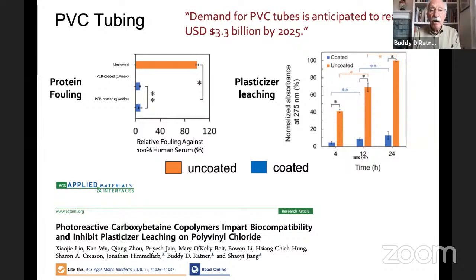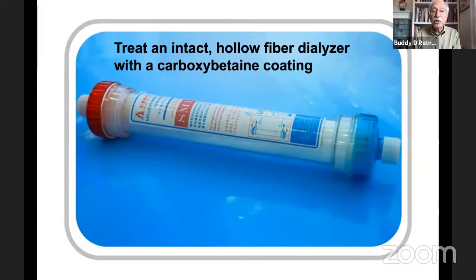But the orange bars in this are the uncoated or control PVC. The blue are coated. And if we look at again, I mentioned we could reduce protein fouling. You can see that our polycarboxybetaine coated materials, the blue, have much lower protein fouling. That's off to the left. Off to the right, we look at plasticizer leaching. And again, the polycarboxybetaine methacrylate, the coated, the blue, greatly reduced the plasticizer leaching. We published this work in ACS Applied Materials and Interfaces. So we're actually treating, along with the PVC tubing, intact hollow fiber dialyzers with this particular type of coating.